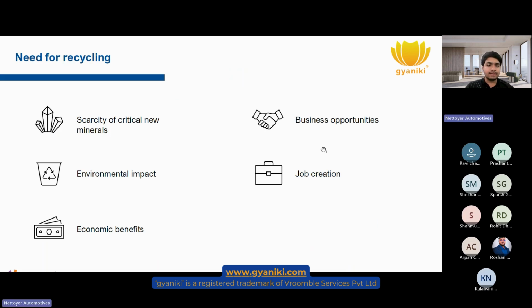The need for recycling is the scarcity of critical minerals. It takes around 15 tons of CO2 equivalent to extract 1 ton of lithium carbonate. So that's the amount of pollution and unsustainability we are looking at. And it becomes very essential to extract lithium carbonate or lithium from the existing cells. Similarly for cobalt, the market is quite dicey. The price of cobalt as a mineral is not consistent. That's the reason it is very essential to extract the cobalt and sell it in the market as well. That would become an economical solution.